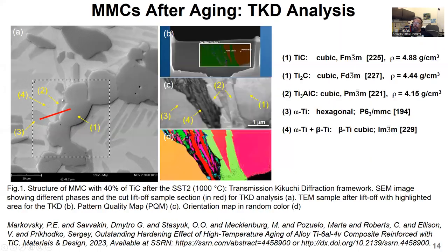Here we see the results of transmission Kikuchi diffraction of the same sample. The area of liftoff, shown here with a red section, covers all four major structural components in this structure. This technique shows the alpha plus beta mix with no doubts on its true morphology and its contribution to the final structure hardness increase due to the Hall-Petch effect.